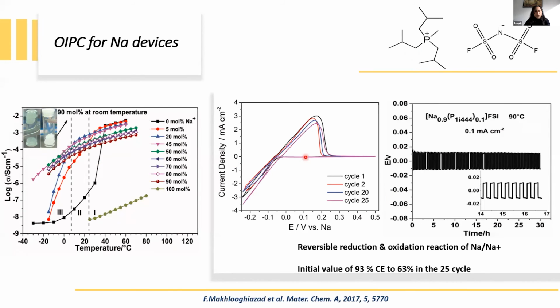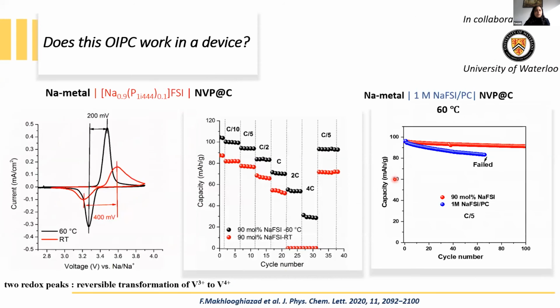So also, for example, here I showed you one high concentration of sodium salt that we measured in a sodium symmetrical cell, and we observed the stripping and plating of sodium is very stable and very reversible in the sodium symmetrical cell. Then we wanted to know whether these plastic crystals can really work in a real sodium device or not. So for the first time, we fabricated sodium devices based on a sodium metal anode and carbon-coated sodium vanadium phosphate cathode material in collaboration with Professor Linda Nazar at University of Waterloo in Canada, whose research group is expert in synthesizing cathode material for sodium devices.